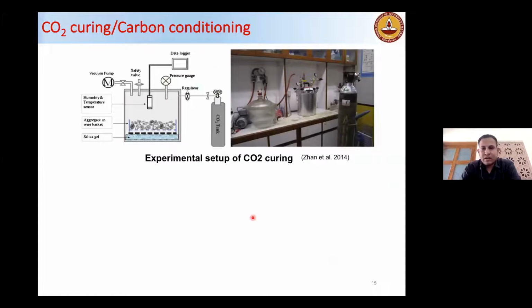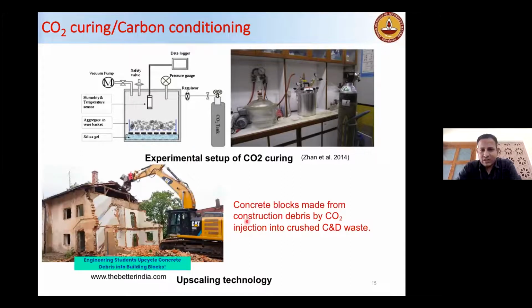Next, a very hot topic these days is the CO2 curing or carbon conditioning or carbonation of the recycled aggregates. So basically there is a chamber, and there is a vacuum pump, and then the CO2 tank. This chamber is pressurized with the CO2, and there will be carbonation of these recycled aggregate, which is a kind of a permanent sequestration of CO2. So this is one experimental setup, but now there are a lot of startups and companies coming with different products such as concrete blocks made by CO2 curing, and there is now a cement also, carbon cured cement, in which the CO2 is injected into the fresh cement.